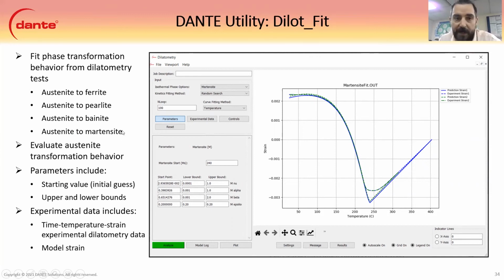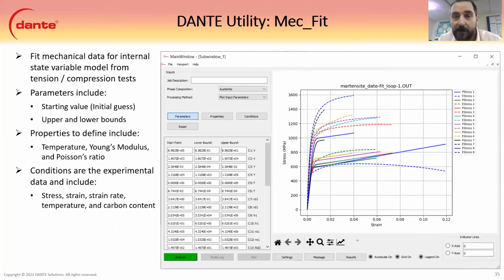We can also fit the time as well for isothermals. And then MechFit works, again, as a fitting utility. Here, there are a lot more parameters to fit through the database. This is for the individual phases, such as the Martensite. You fit the individual phases to the stress, strain rate, temperature, and carbon content. It's all a function of all those parameters.